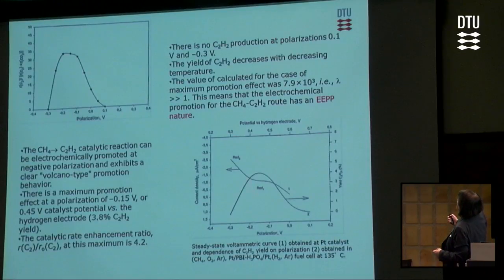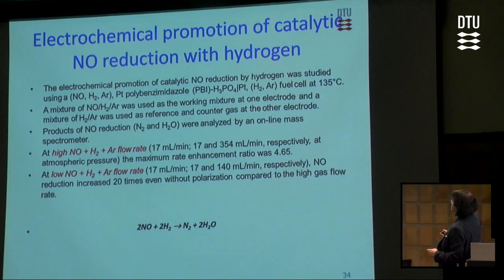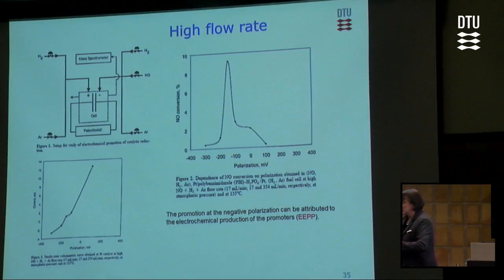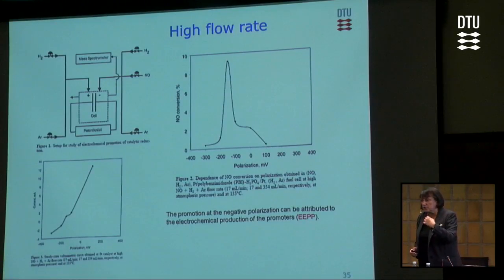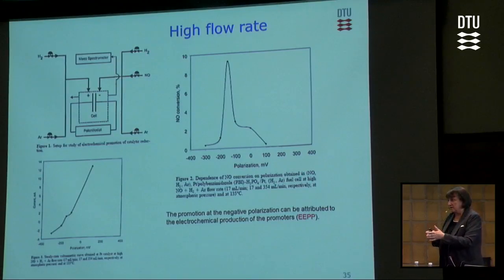This is CO, and here I can show that we actually have a promotion effect when we have a reduction of protons, negative polarization. So it's a pure case of double E, double P. Another one is a reduction of NO with hydrogen. And I just use here slow flow of reactants and high flow. It's about time of contact. If we have slow flow and long time of contact, we just use all active sites. So, for the catalytic reaction it will be good if you take protons from the interface.